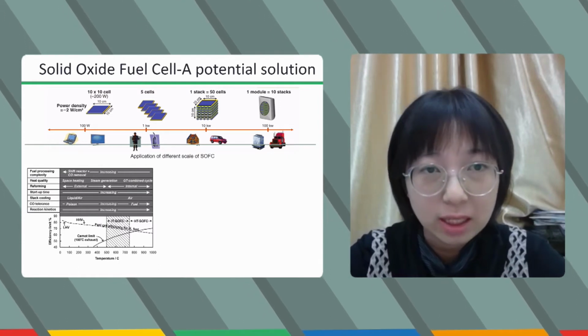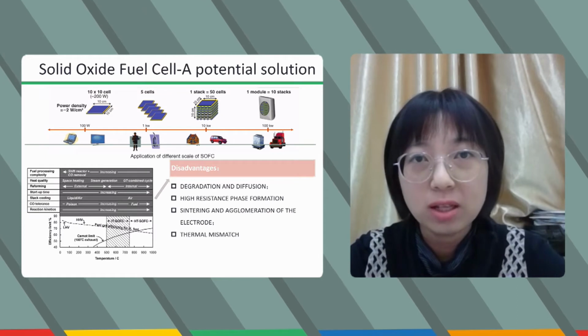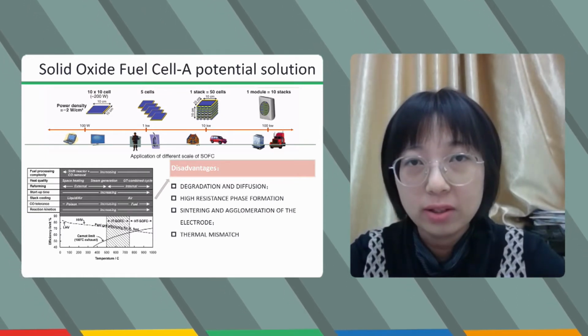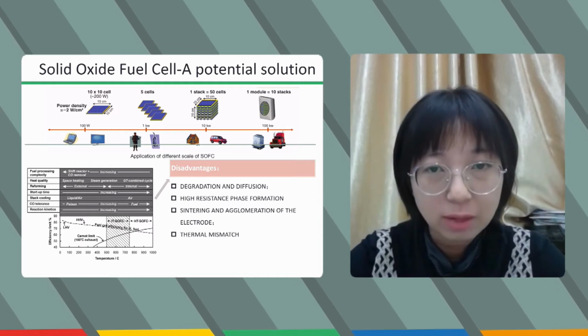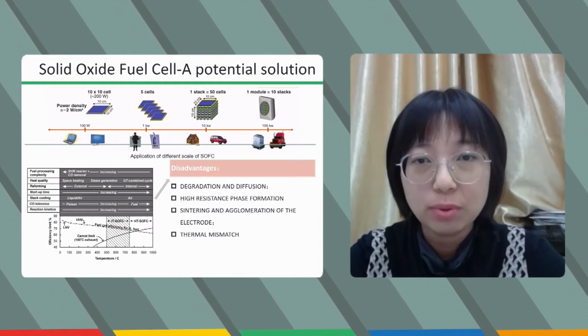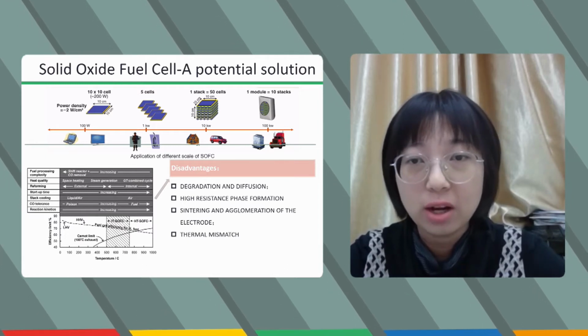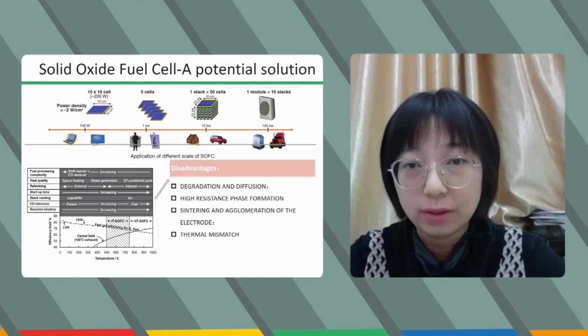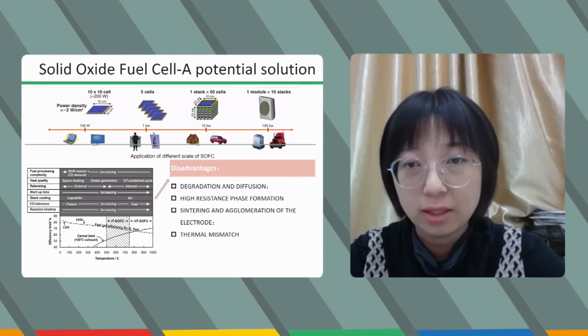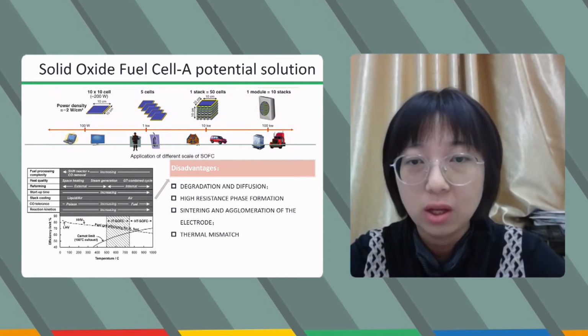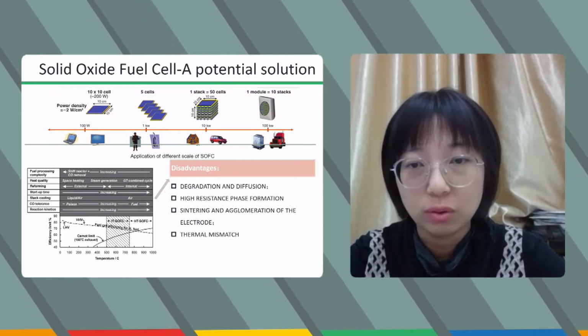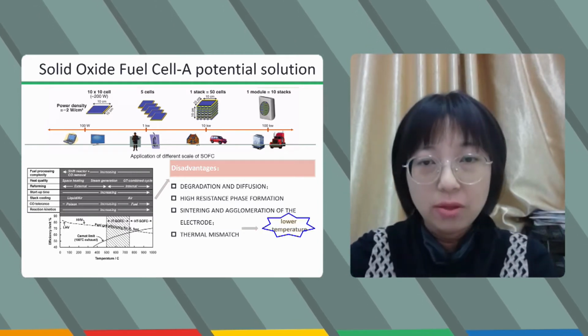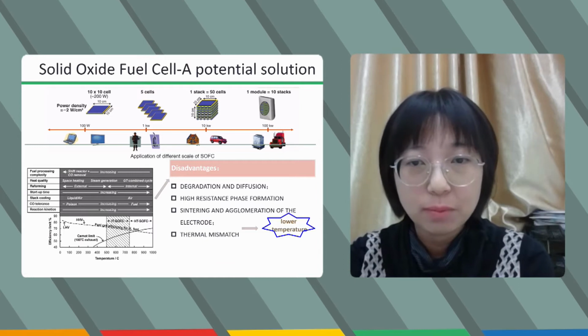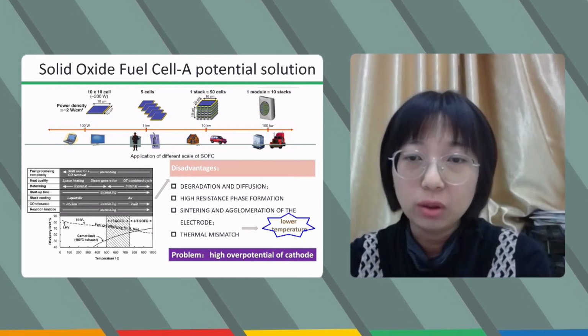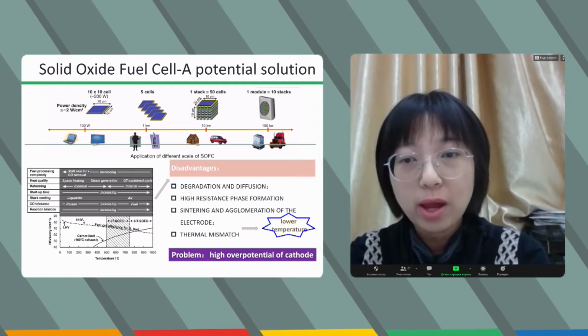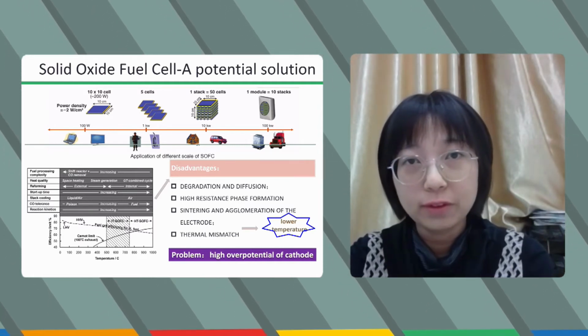However, the solid oxide fuel cell is a kind of fuel cell that operates at relatively high temperatures. At relatively high temperatures, it has to solve some problems, such as degradation, diffusion, high resistance phase formation, sintering and agglomeration problems of the electrode, and thermal mismatch. Therefore, it is now developing towards a lower temperature range. However, at a relatively lower temperature range, we have to solve the high overpotential of the cathode.